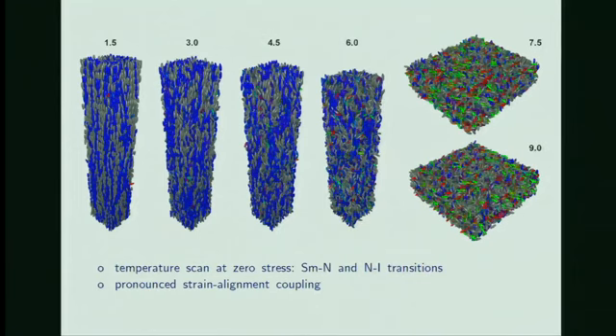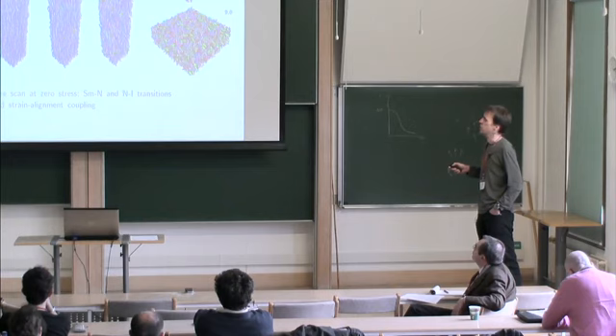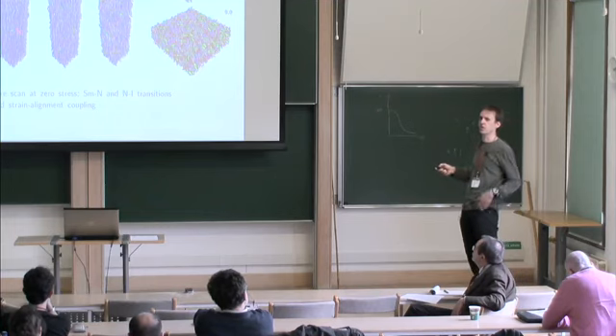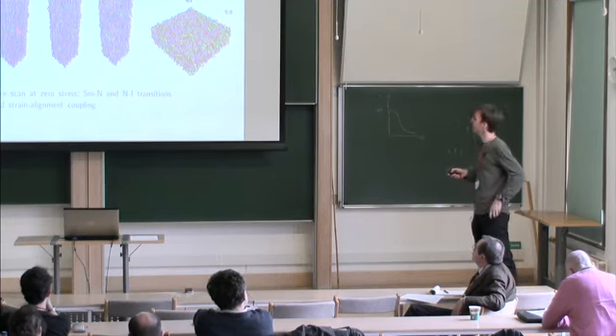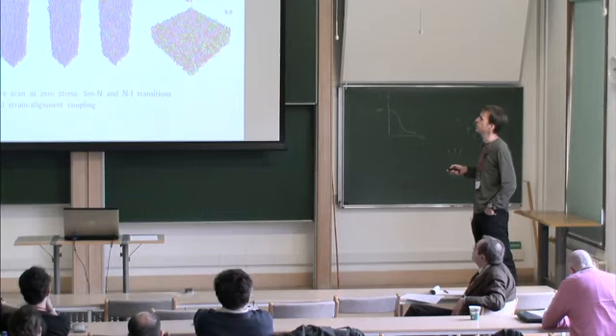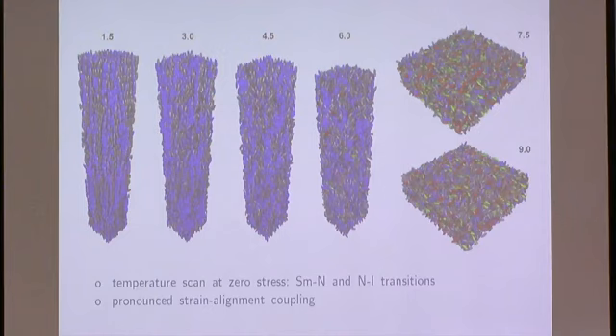Now, dropping the cubic simulation box constraint, we let the system evolve as it wants at zero stress, and then for different temperatures we have these different snapshots. So for example, at T star, temperature equal 3 units, dimensionless units, we end up with a system that's pretty much elongated along the z-axis. You can see that the system kind of recovered the previously imprinted z-axis, and there is a lateral compression to maintain volume. So the gray particles correspond to the swelling monomers, and the colored particles correspond to the ones belonging to the network.